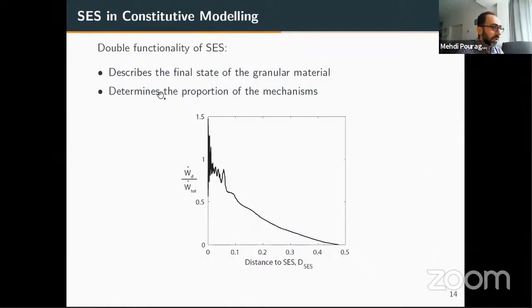So this idea has actually been used in constitutive modeling. We developed a purely constitutive model for granular material based on this idea of SES, and we use the Euclidean distance to this manifold as a state variable that gives us the proportion of different mechanisms that change the behavior of the material. For instance, here we are seeing the percentage of the external work that is being dissipated due to frictional mechanisms, and we see that at the beginning it's 0, and as we reach the SES, as the distance is decreased, it approaches 1.